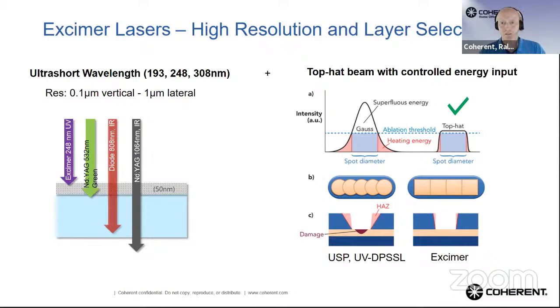The other thing is, so it's like a package which is provided by the Excimer lasers, is that it's very easy to make a top hat profile from this laser because it's a multi-mode laser. And with a top hat profile, you have main advantages being if you want to fill a large area with top hat, say square or rectangle spots, you have a high fill factor and you do not need high overlap of the shots. So you're very fast and you really have a smooth application of your energy density over the area. And also you avoid superfluous energy in the center of your intensity distribution, like in Gaussian profiles. And so that also helps to be very layer selective.